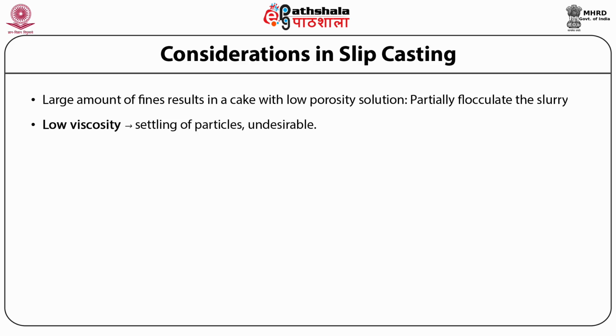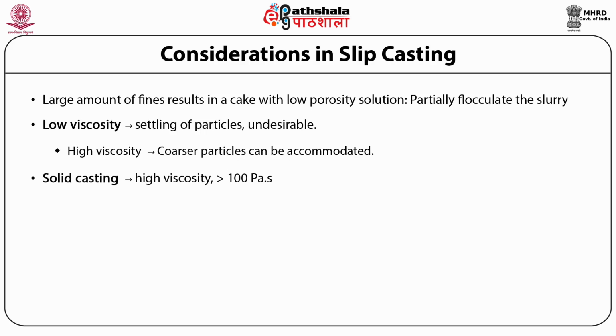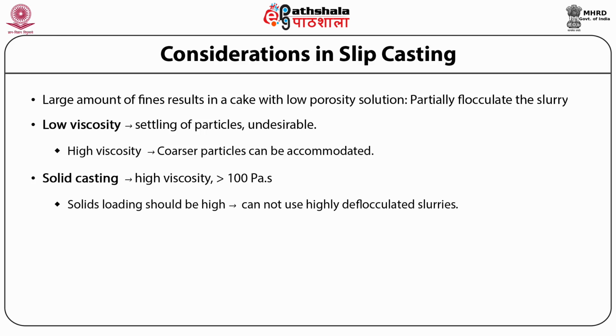Second, if the viscosity is too low, the particles would tend to settle to the bottom and the available casting time would be small. In slurries with a high viscosity, larger particles can be accommodated. Third, it is desirable to keep the solid loading in the slurry as high as possible so that less liquid has to be removed. The solid loading depends on the thickness of the double layer around each particle. In a highly deflocculated slurry with fine particles, with each particle having a double layer, the particles cannot be brought closer than a certain distance, and so the solid loading is limited.